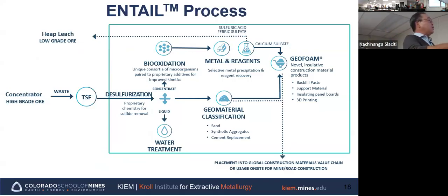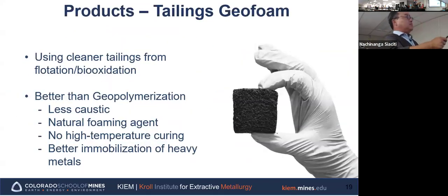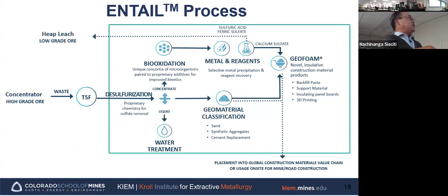So this is the overall flow. In a concentrator, waste material tailings come into a tailing storage facility. And then by desulfurization, we can get a concentrate. The concentrate goes to bio-oxidation or bio-leaching using specific microorganisms to oxidize the sulfide sulfur to sulfate and then produce sulfuric acid. And then also oxidize the ferrous iron that comes from pyrite and other iron sources to ferric iron, and then ferric sulfate in a sulfuric acid solution will be formed. So we can create those two key lixiviants for copper operations.